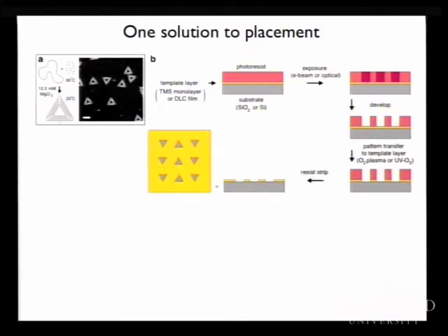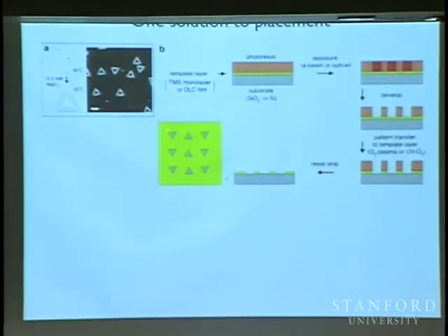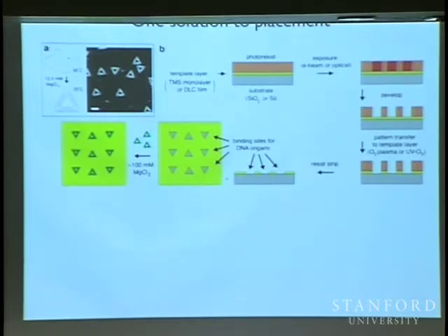And so what you're left with is a substrate with some background in yellow and then spots that are the shape of DNA origami written by E-beam, okay? And these spots are supposed to be binding sites for DNA origami. So in the presence of enough magnesium, we have the same kind of charge effect we have on mica. So the spots are nominally negatively charged, the magnesium is positively charged, and it cements the DNA origami on those spots, right? That's the goal.